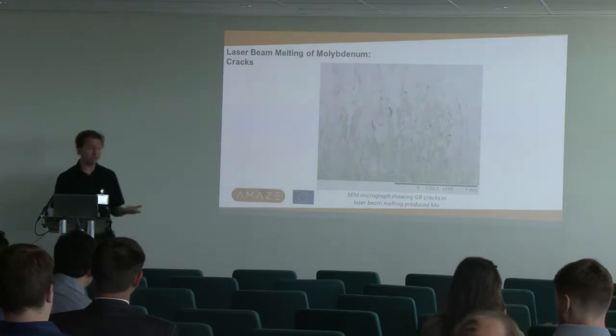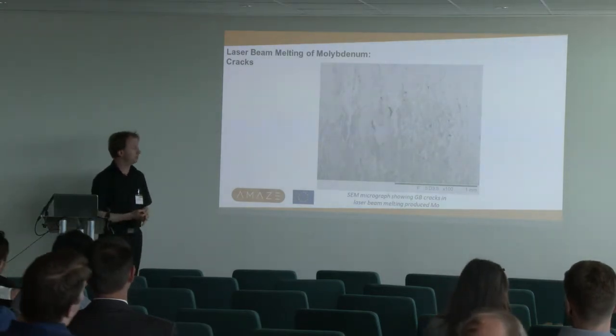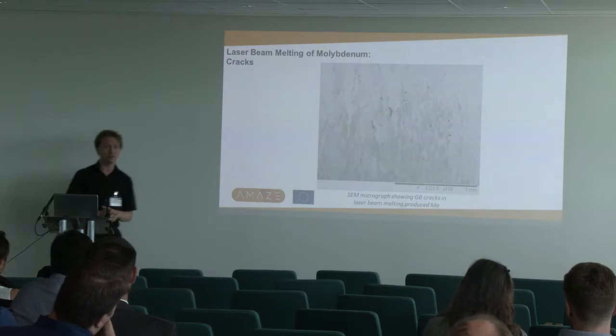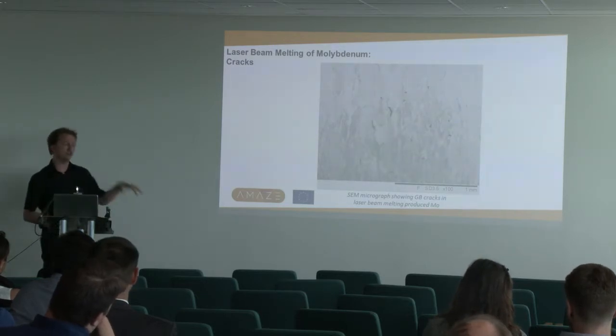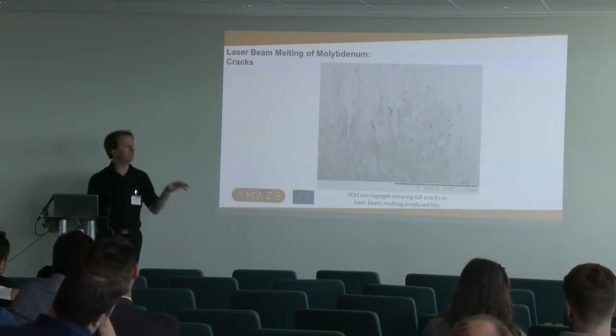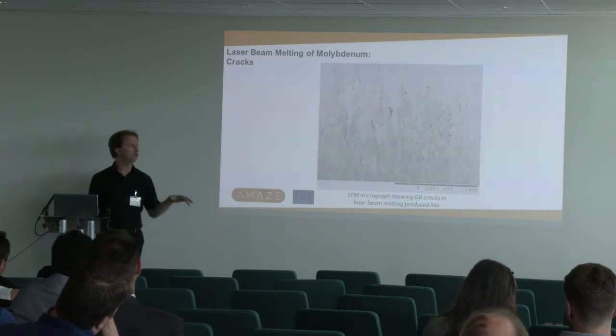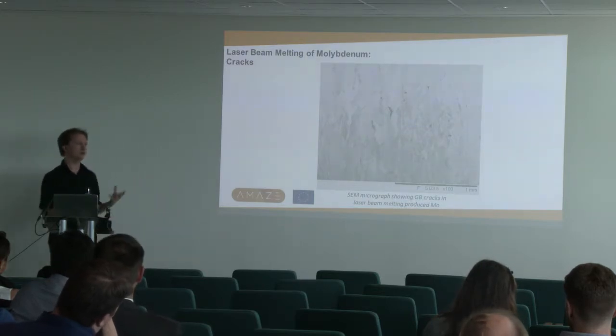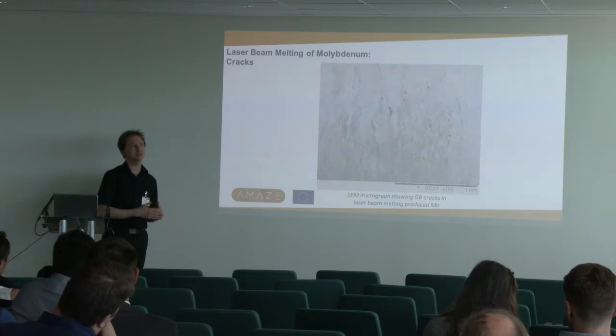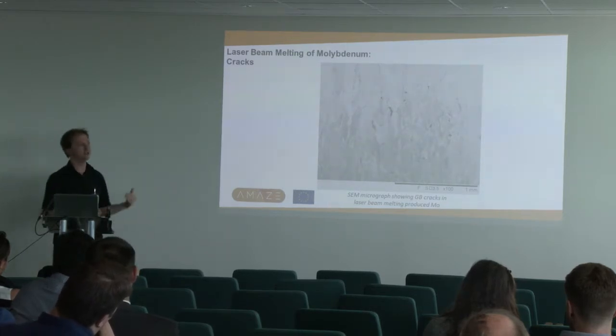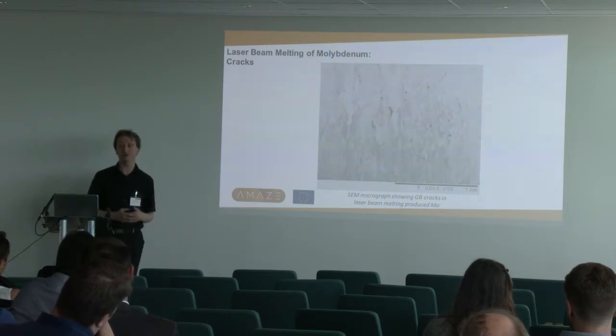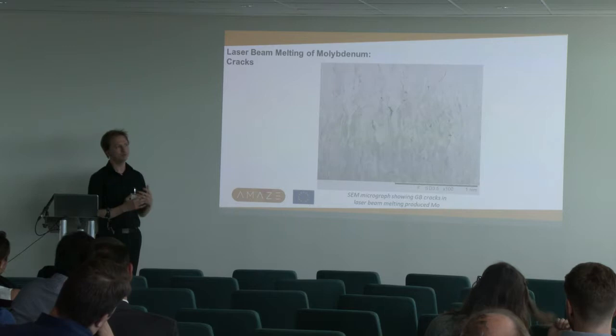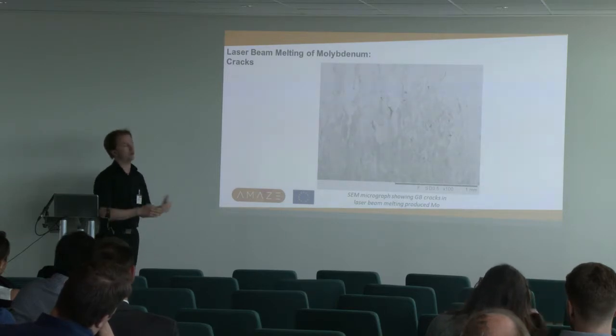The material does crack, and there's not a huge amount that we can do about that with the technology in its current configuration. So basically, echoing what Dave was saying, we've got to a point where we're saying, look, we've reduced the porosity, we've reduced the cracks as much as we can with the machine in its current configuration. And Amanda's work is going to carry on with these refractory materials and try to modify the process, and do some, I guess, process development type work to try and reduce that cracking further.